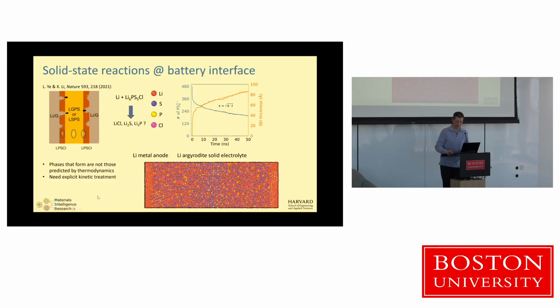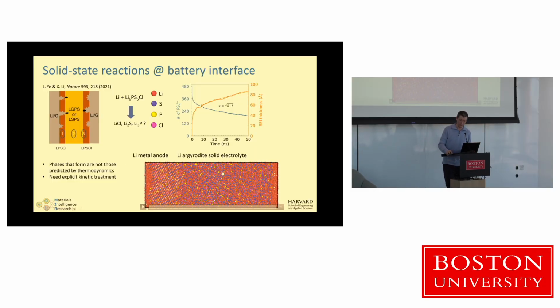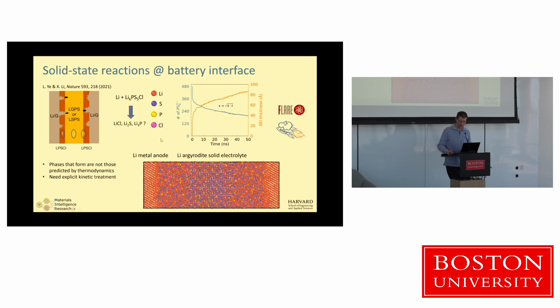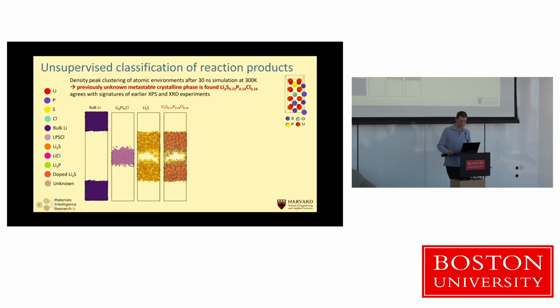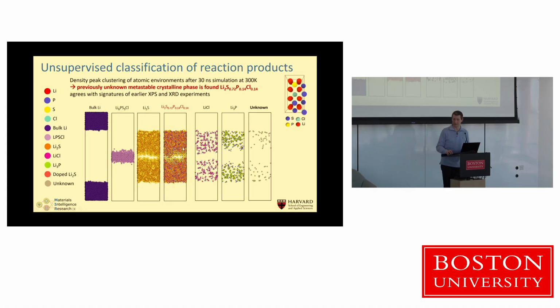You can run it at essentially this kind of representative geometry of a battery, and see that there's a very fast degradation reaction that consumes both the electrode and the electrolyte, forms additional phases which we didn't expect actually. And so this is one of those examples where you learn from the simulation what the mechanisms are, and then you see formation of something that is a product which may not be a good thing because the battery will not conduct ions anymore. And you can do this calculation and then afterwards analyze what actually happened. Like, your electrolyte got consumed, your lithium electrode got consumed, and you have these additional phases that started growing very rapidly, even at room temperature, in about 50 nanoseconds. There's this thick layer of junk that you don't want, but you actually understand what it is, hopefully better.